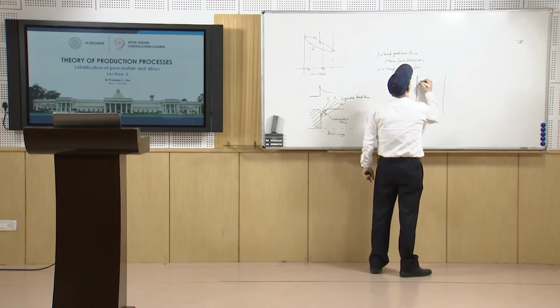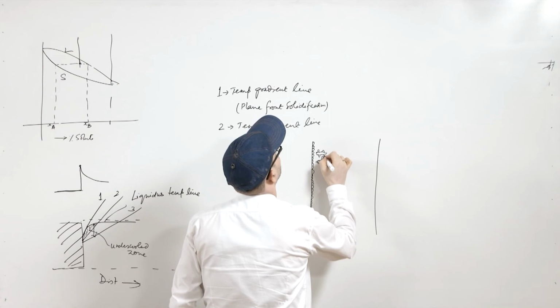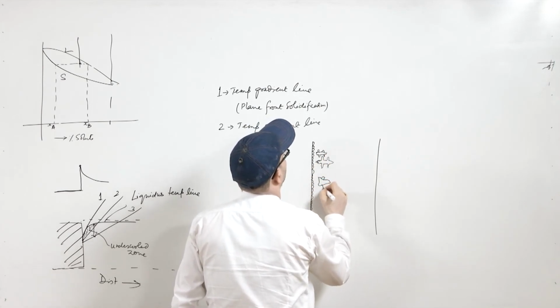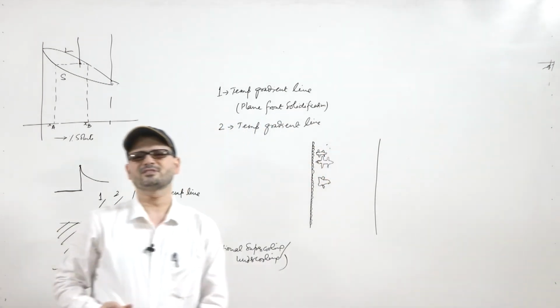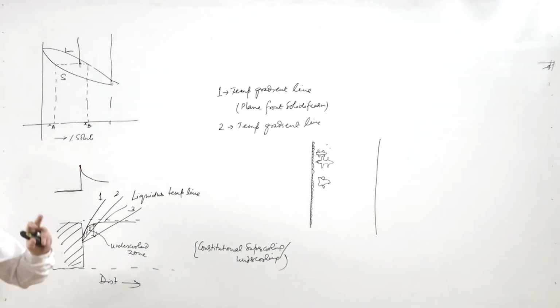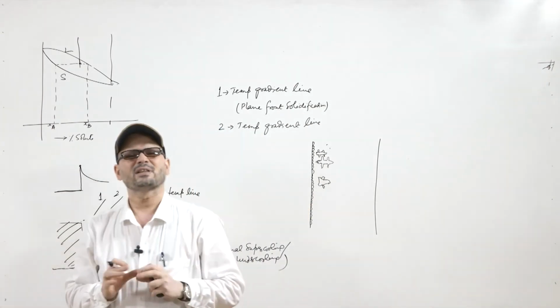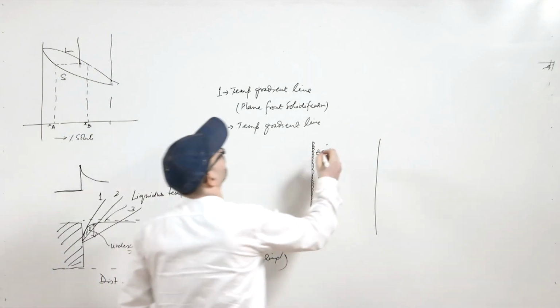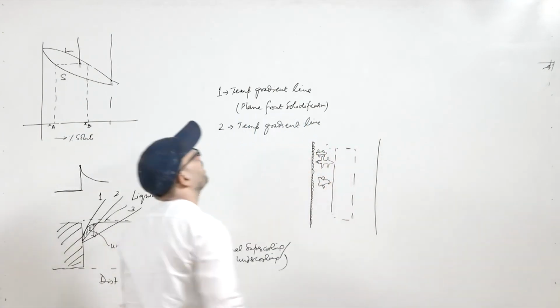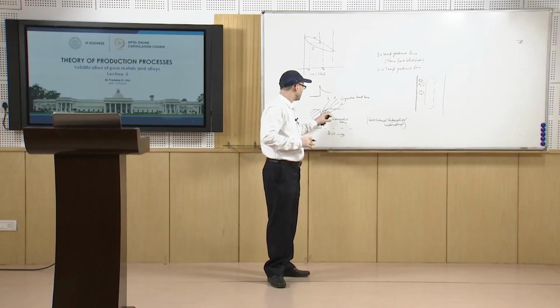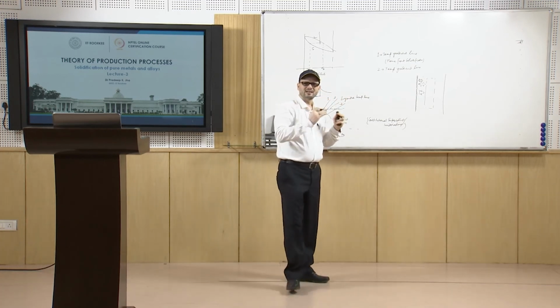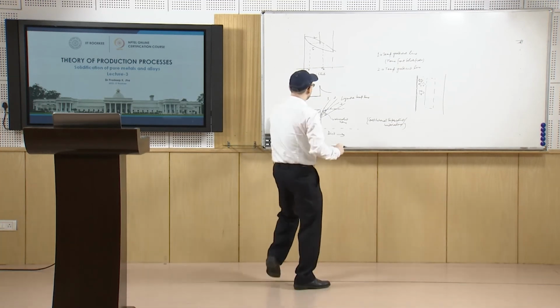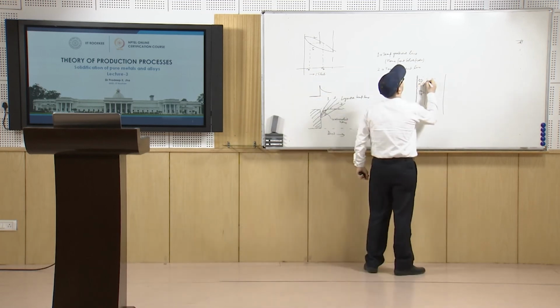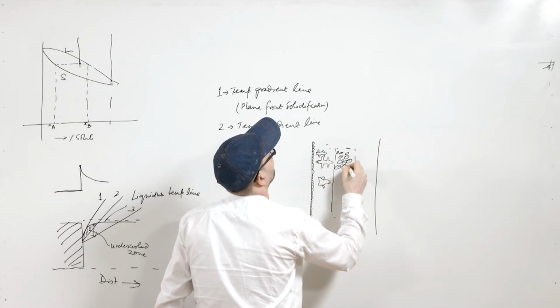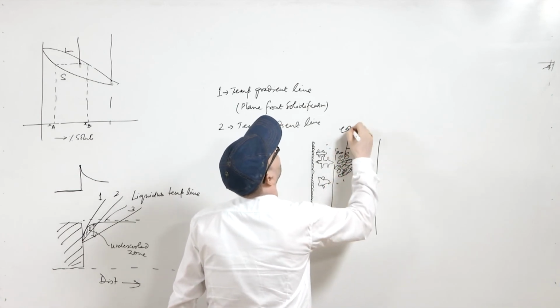So, in this case you will have many places with these kinds of spikes or tree-like structures. This way it goes, and you will have the growth of columnar grains, but then the formation of these spikes or dendrites. So, that is known as columnar dendritic structure. Now, what happens in the middle zone? In the middle zone the cooling rate becomes even slower, as we know that as we go towards the center portion the cooling rate becomes slower. So, this differential becomes even more. That is why here you again get the equiaxed type of structure. So, this will be equiaxed dendritic, and this is columnar dendritic.